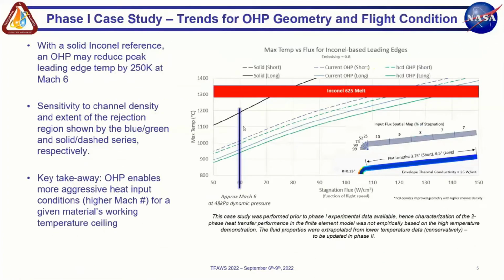Back in the phase 1, we did a series of finite element simulations, and one of the takeaways was that a solid Inconel leading edge structure isn't really a competitive solution for hypersonic leading edges. But if you took that sort of metallic hot structure and simply converted it to include the embedded microchannels and working fluid and had a functional OHP, then you could drop the peak temperature at the leading edge by 250 K at around Mach 6. We looked at various sensitivities to different channel densities and transport lengths, shown by these other series. But the key takeaway is that the OHP enables more aggressive heat input conditions, related to higher Mach number flight conditions, for some given material's working temperature ceiling.